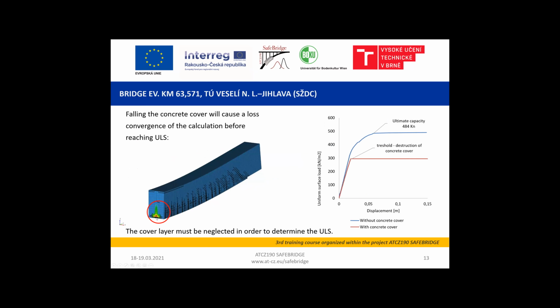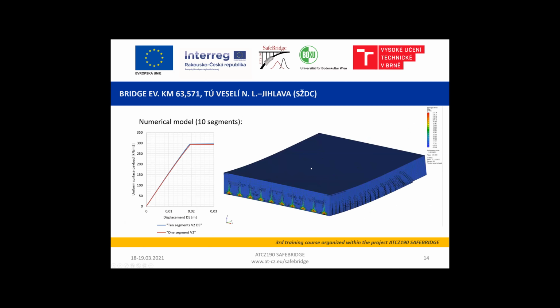Of course, if you model such details of cross-section geometry, we can expect that the bottom layer of concrete will eventually fall during the analysis, and it will cause loss of convergence for low performance concrete. So it's recommended not to model it at all, just to consider the lower layer of concrete as a dead load, and not place it into the model. We can see some comparison of a calculation with the concrete cover and without it, and we can see that it's very similar. So for subsequent analysis, the concrete cover was neglected.